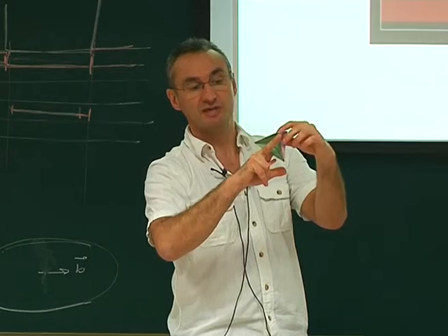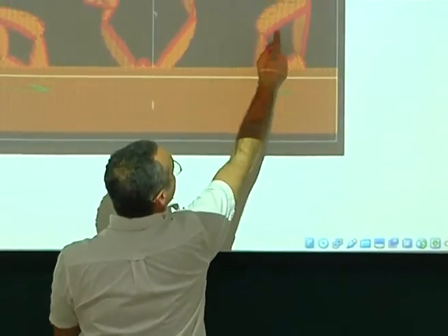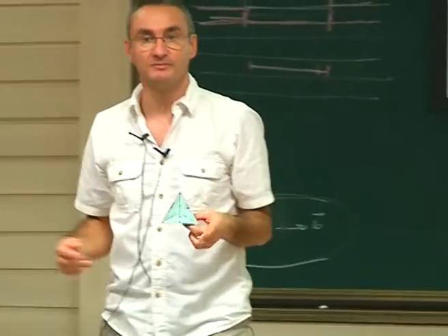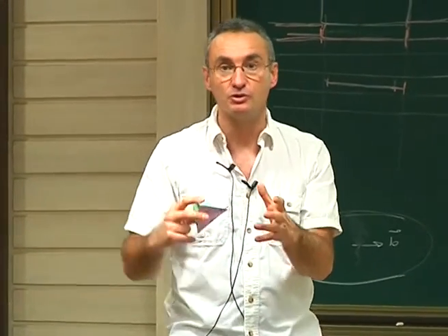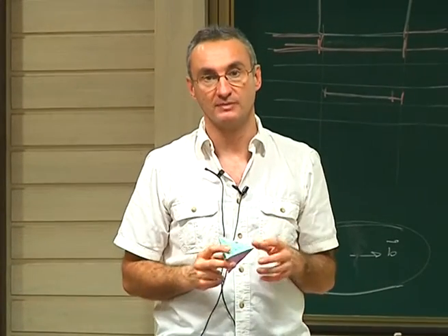Okay? So if you take these two, this corresponds to the acute part of this, and the obtuse is just, when you close it, the opposite side with the two. So here you have an acute angle. So you have acute and obtuse angles. So it's not a square loop. And you cannot make it round or whatever. If it was round, then the loop is not a perfect loop. It will not be in a {111} plane, so you have some non-conservative motion. So if you want to have only conservative motion, you need to have this shape. Okay.